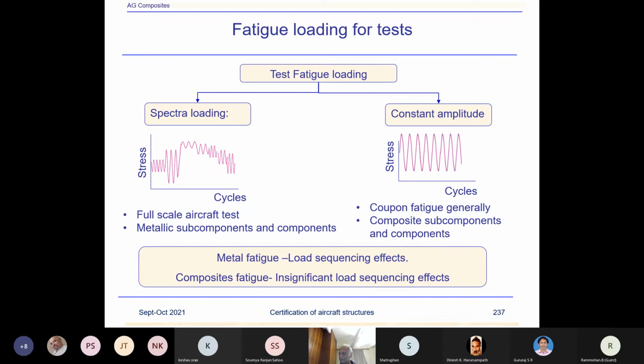However, if we are trying to test a composite structure, we can take advantage of one phenomenon in composites: generally composites are virtually not affected by the load sequencing. Whether you go high-low or low-high has an insignificant effect on the life. But in metals, it can have a drastic effect, as I showed with the Comet failure test, where they caused an overloading effect, which gave an artificially very high life. So it is very risky in metallic structures not to use a proper type of fatigue spectrum.